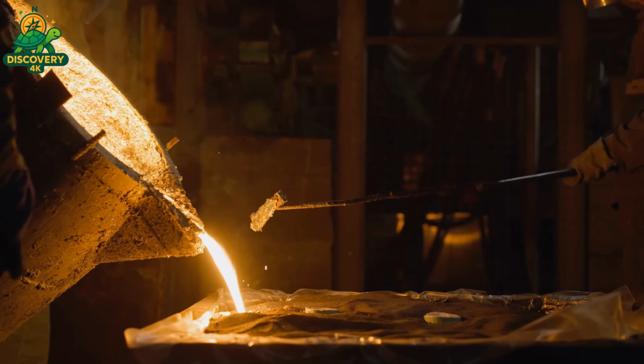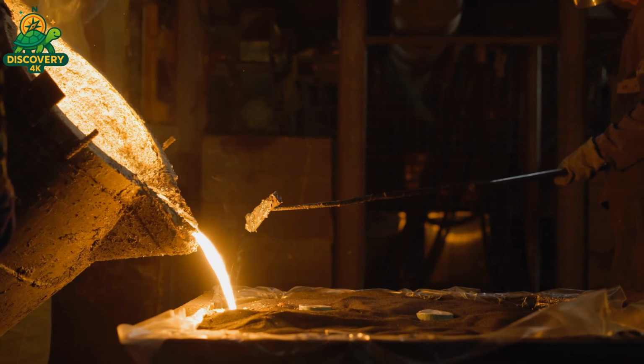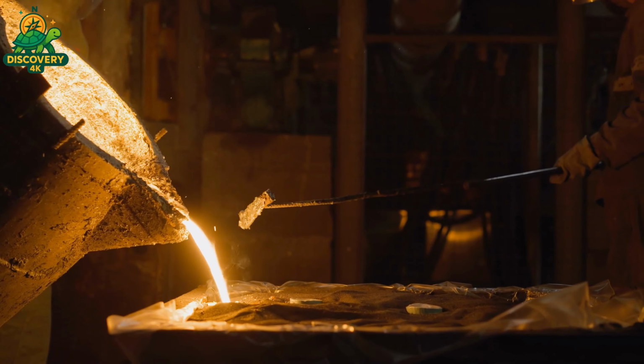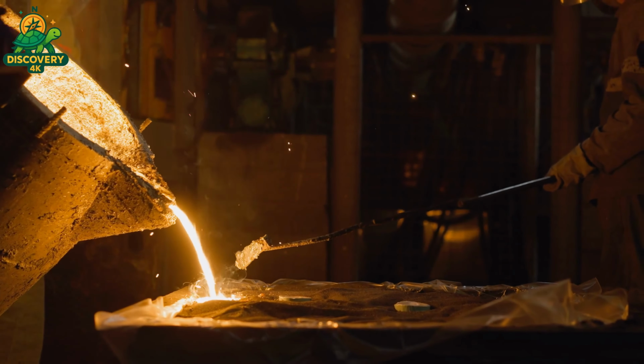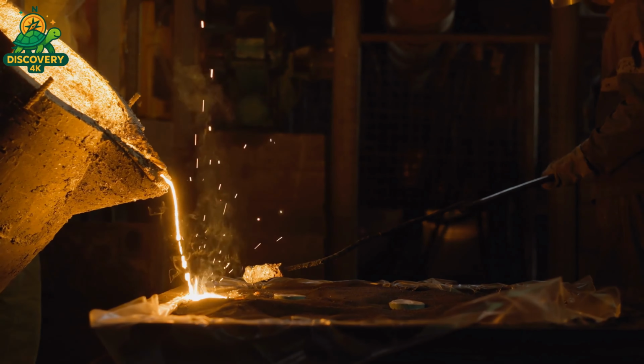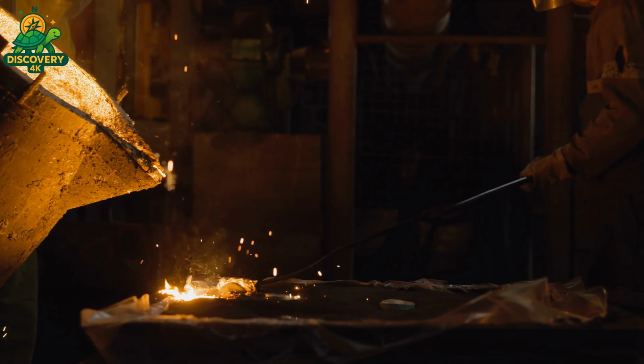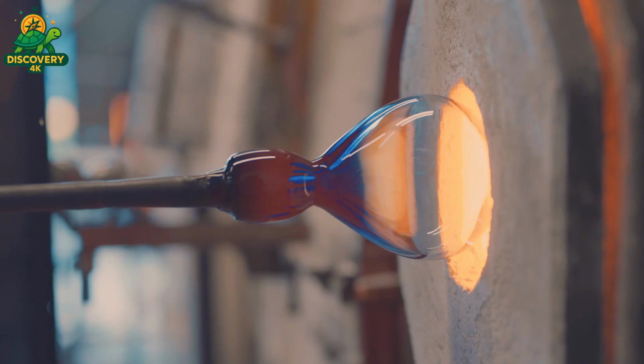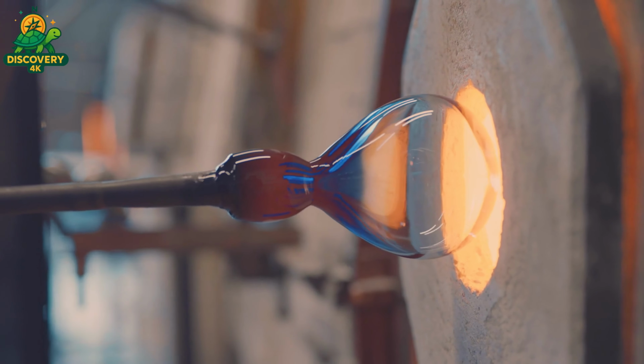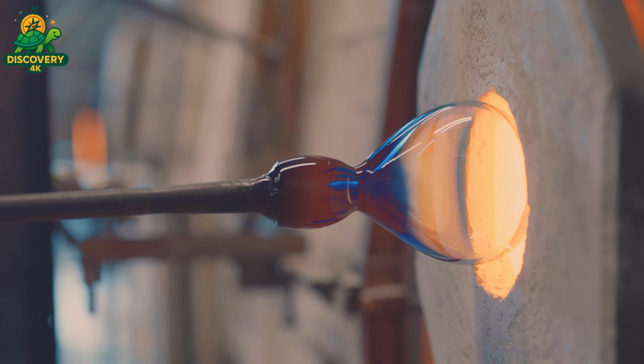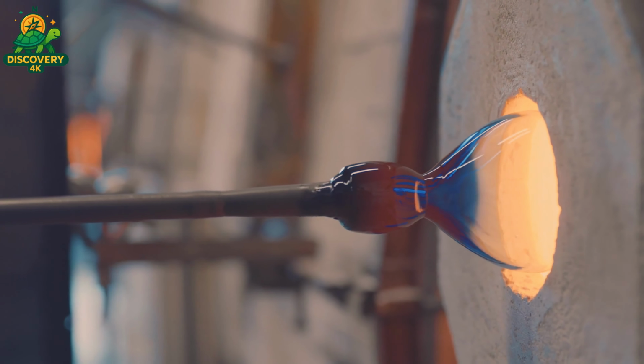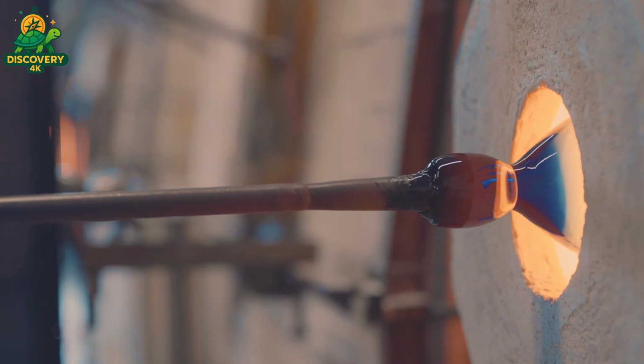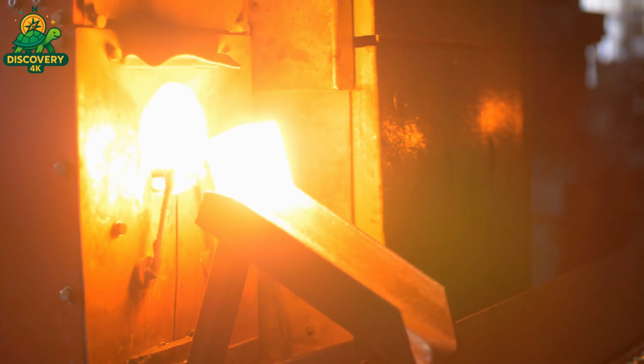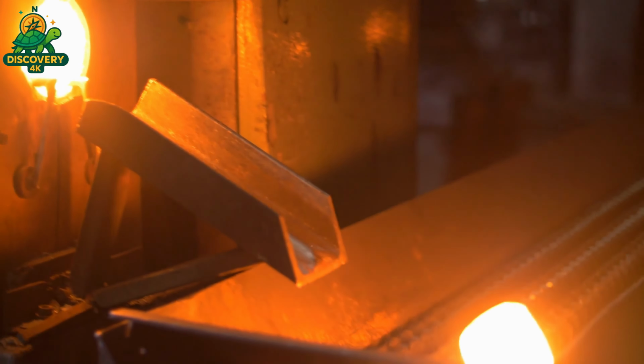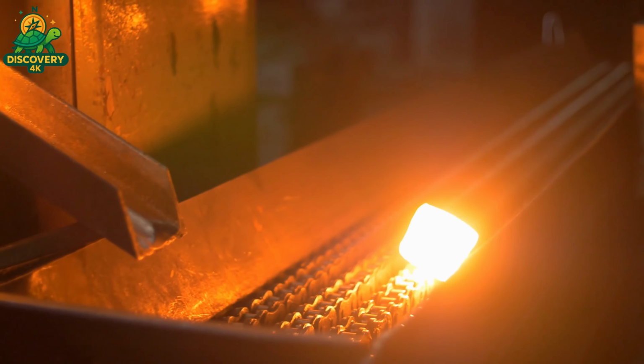To ensure quality, a step called fining is critical. This removes gas bubbles and unmelted particles. Fining agents like sodium sulfate or antimony oxide may be used, or the molten glass may simply be held at high heat to allow bubbles to escape naturally. After the glass is fully melted and fined, it flows into a refiner zone, a slightly cooler area that reduces the temperature to about 1,050 degrees Celsius. This creates the ideal viscosity for forming, thick enough to shape, but fluid enough to fill molds without defects.